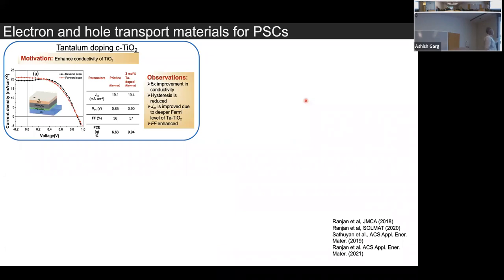One of the works that we have done in our lab is to increase the conductivity of the bottom TiO2 layer. Titanium oxide, as you know, has rutile and anatase phases. Titanium oxide is not very conducting. It's an N-type material, but not highly conducting. When you dope tantalum into the TiO2 lattice, tantalum is a +5 element, so it causes N-type defects.